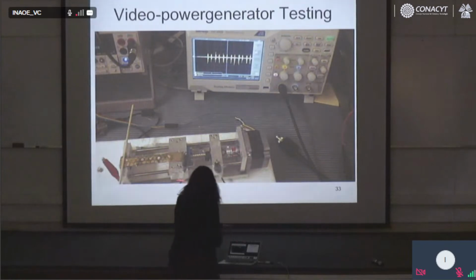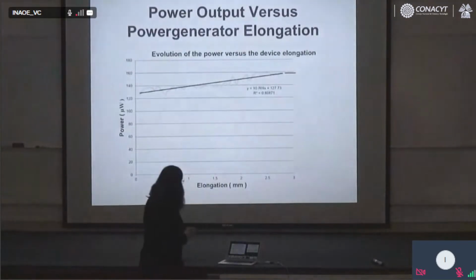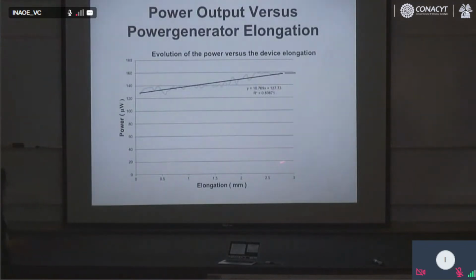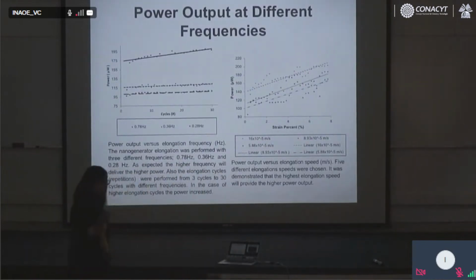And then what we did with this motor, we stretched only like 3 millimeters, not too much. When we start stretching, we saw the power is increasing, of course, because we stretch. And then we cannot get more power after 3 millimeters. We decided not to stretch more, not to destroy the sensor, because probably the cracks in the piezoelectric material were so big that the sensor was not able to produce more power. But it was nice. And in the literature, the other sensors, the other power generators like this one, have even less than 200 microwatt.